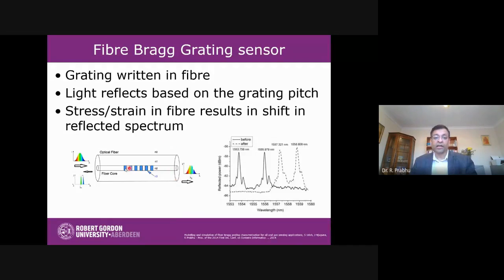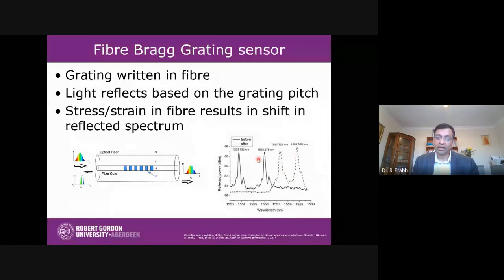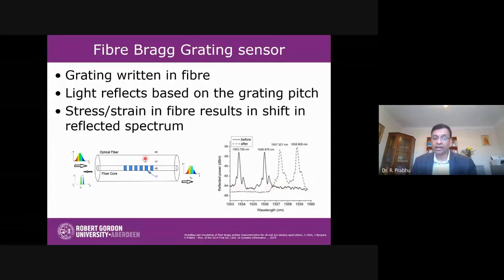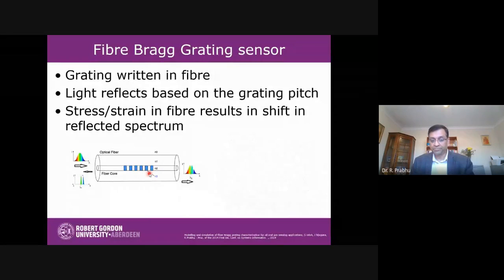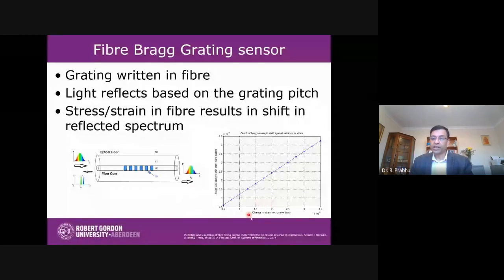So if we send a signal, you can get a reflected signal like this based on the structure of this grating. And if we apply a strain, this peak might shift from here to here. So there are two structure gratings, one reflecting at this wavelength and one reflecting at this wavelength. And because of the strain, that might shift from here to here, indicating something is changing around this. The change in strain can be correlated to the shift in the reflected spectrum. And normally, it's a linear function.